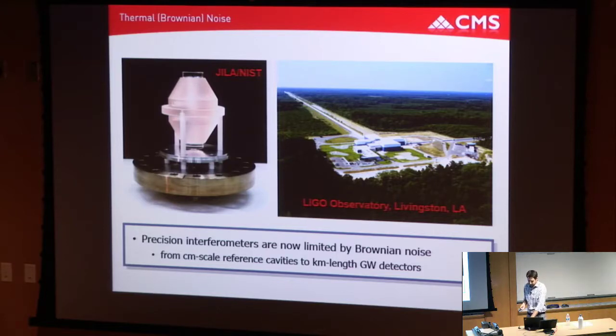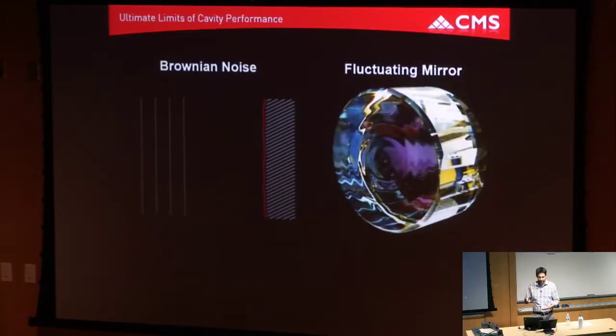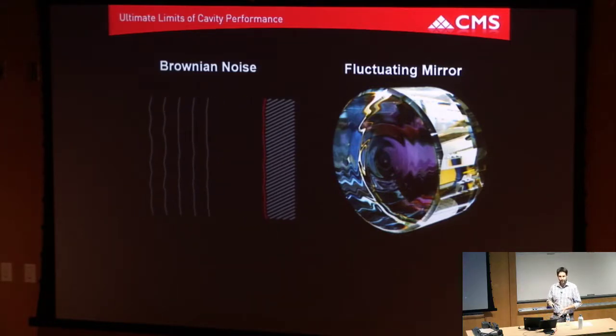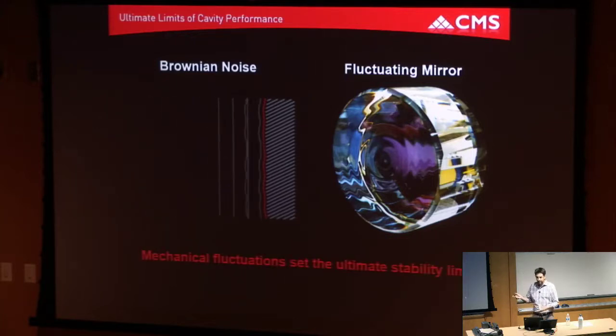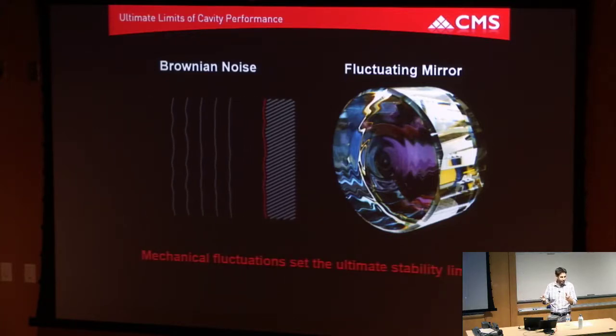And it's conceptually simple to understand. You have an optic that's sitting at some finite temperature, and the thermal bath is constantly pumping the mechanical modes of that body. So you have this forest of mechanical modes, flexural modes, surface acoustic modes, all kinds of mechanical modes that are actually pumped by the thermal bath. And this is going to dither the length of that cavity. And the one thing that I think is not immediately obvious is that these mechanical fluctuations set the stability limit of the cavity.